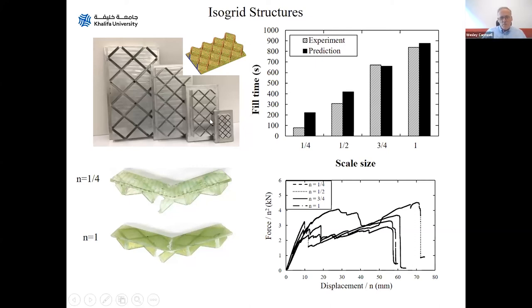But one of the challenges making samples like this, especially small scale samples, is when you're cutting woven fabrics to very small size, they quickly disintegrate in your hand. And so you end up putting something that really doesn't look like a woven fabric into these slots, and that changes the permeability and that changes your fill time as well. But in the larger samples, the fill times were in accordance with what we would expect and how we'd expect that to scale.